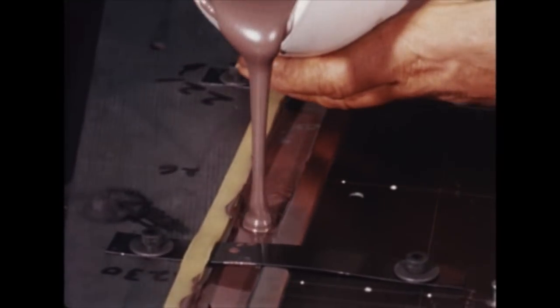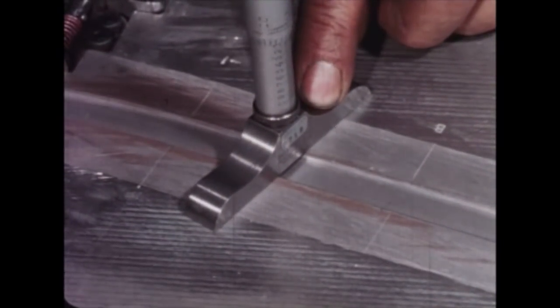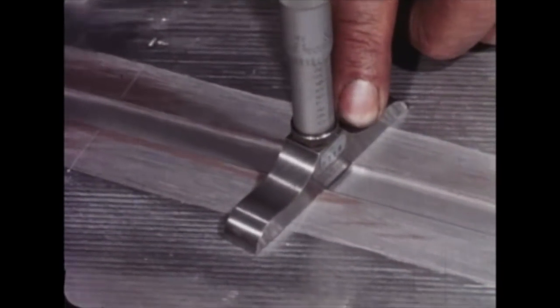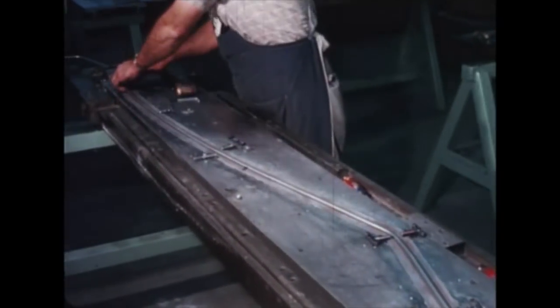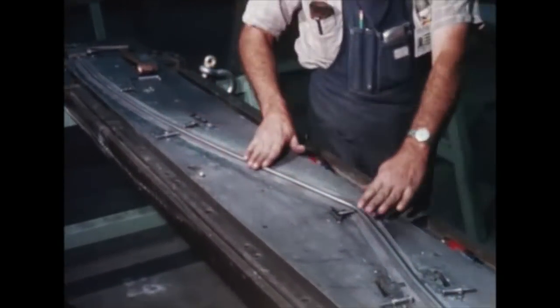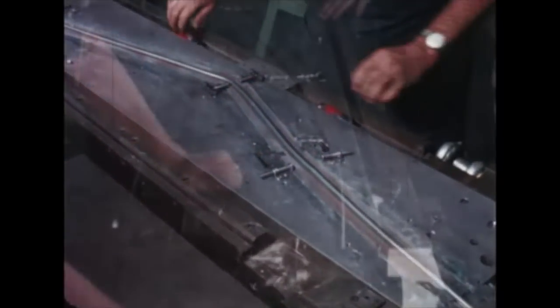The cavity is filled with an epoxy resin. This filler cures and hardens at room temperature in approximately 12 hours. It will withstand 25,000 psi compressive stress. The mold in which the tube is formed can be made either by pouring the epoxy around a master tube set in place, or by pressing the tube into the mixture prior to hardening.